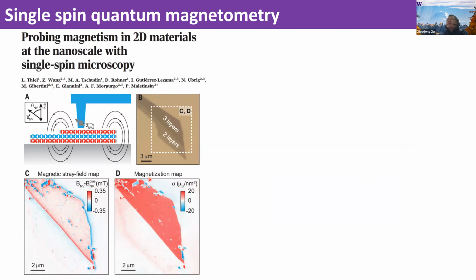So this calls for a nanoscale magnetometry to resolve the spatial magnetic patterns. This technique, first of all, should have enough sensitivity to measure this nanomagnetism. The second is it should have the spatial resolution to measure the domain size. And the last one is it should not provide any kind of dynamic feedback to perturb the magnetic states. So the community already provides such a technique, which is called single spin quantum magnetometry. Basically, with an NV center hosting a single spin, an NV center in a diamond. And this single spin is very sensitive to the magnetization. And the group led by Maletinsky